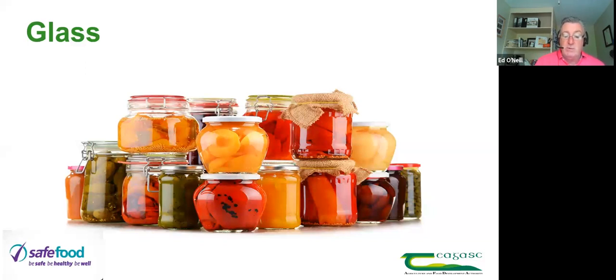Recycled or broken glass, called cullet, is also used in manufacture and may account for as much as 60% of all raw materials used. Glass containers used in food packaging are often surface coated to provide lubrication in the production line and eliminate scratching or surface abrasion and line jams. Glass coatings also increase and preserve the strength of the bottles or jars to reduce breakage, and this improved break resistance allows manufacturers to use thinner glass, which reduces weight and is better for disposal.